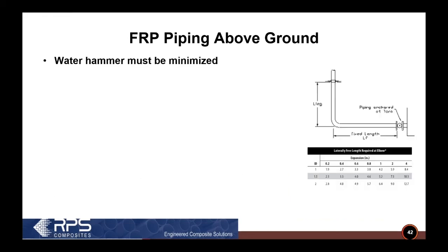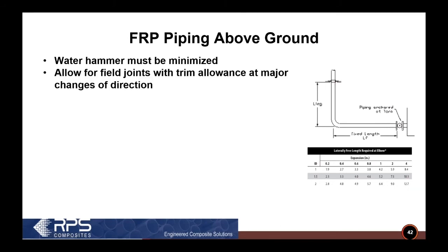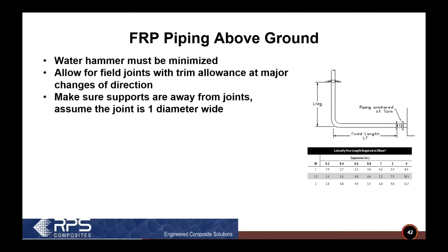And above ground FRP pipe, water hammer is a no-no in FRP pipe. You want to try to minimize that as much as possible. It's not as forgiving as it is in metallic piping, again, because it's not elastic like metallic piping is. You've got to allow for field joints and changes in direction. So if you had two flanges, you can't just draw the flange in place to make it fit. It's actually got to fit in place unstressed.